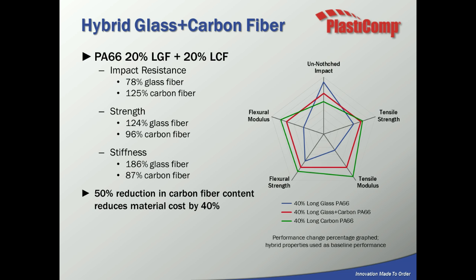And when we look at strength, we get 124% of glass fiber, and we maintain 96% of the strength of a straight carbon fiber reinforced material. From a stiffness standpoint, you can see there's a huge increase in stiffness with the addition of the carbon, but we maintain about 87% of the carbon fiber stiffness with a hybrid formulation. So with a 50% reduction in carbon fiber content, we can actually reduce the cost of the material by about 40% as well.